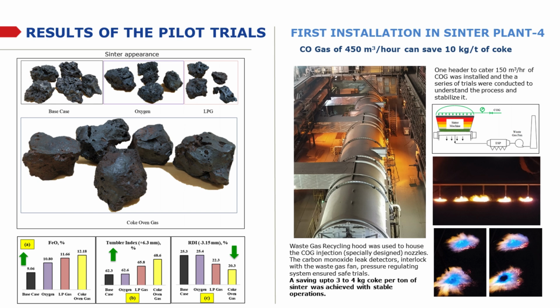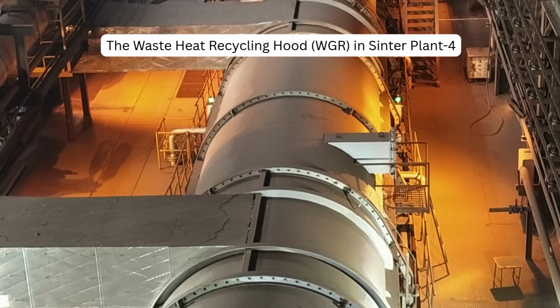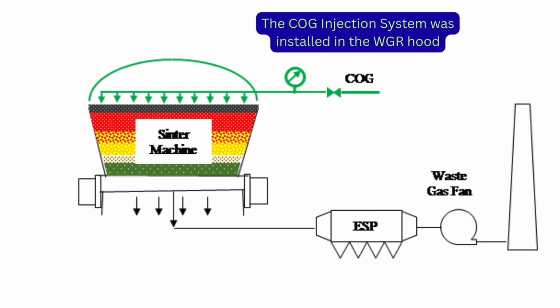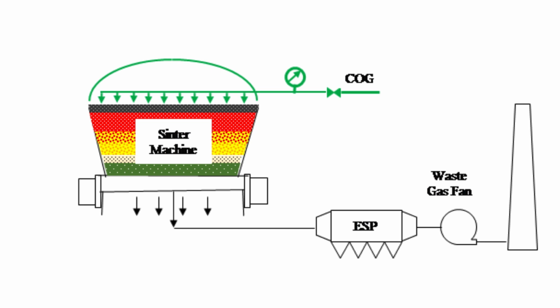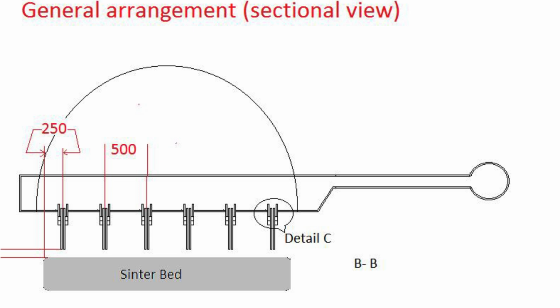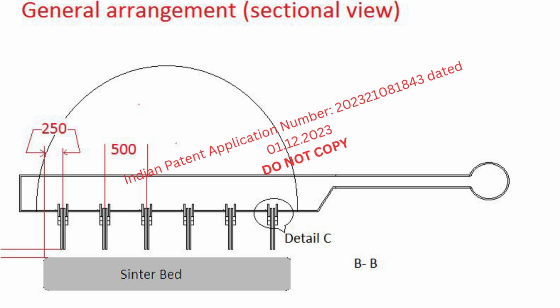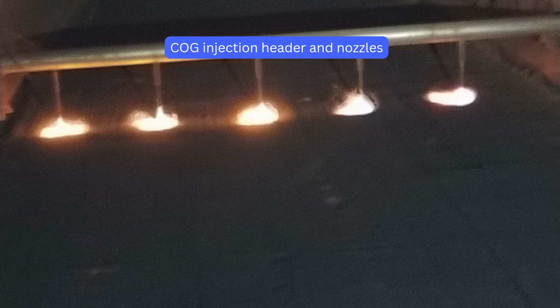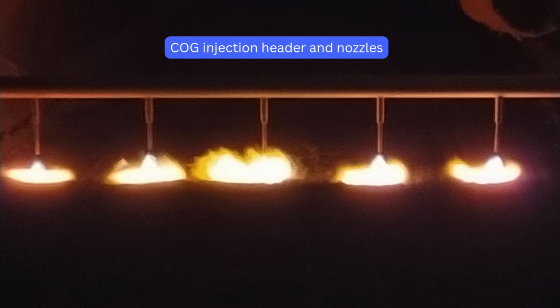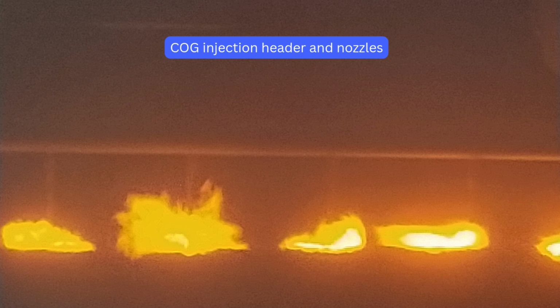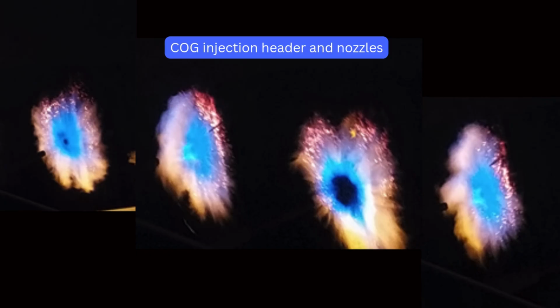The voice of the process indicated improved thermal regime and mineralogy. After proving the concept, we scaled up by designing COG header, nozzles, and installed in Sinter Plant 4 in 2020 during COVID times. This is the scheme of the injection system. The design involved three headers of 150 cubic meter per hour capacity each and nozzles to inject COG close to the sinter bed. Multiple trials were conducted to fine tune the process, and we continued injecting for more than 1.5 years.